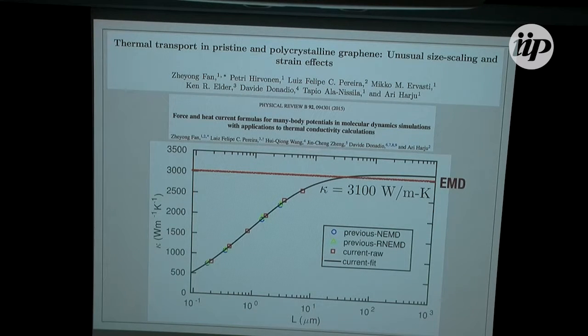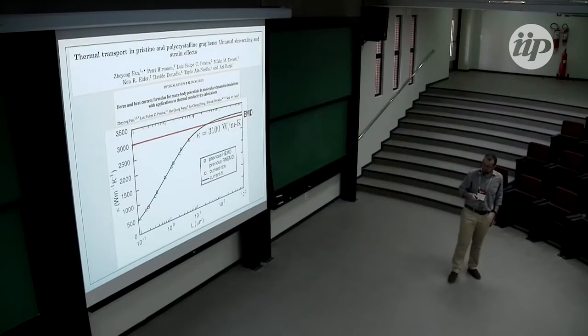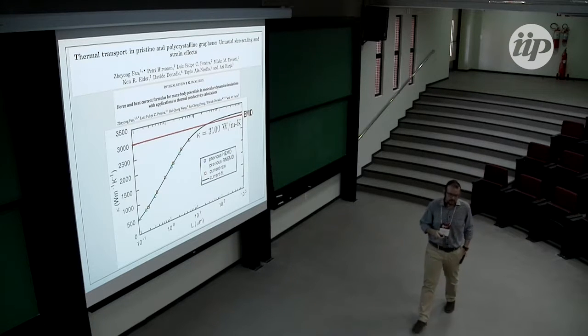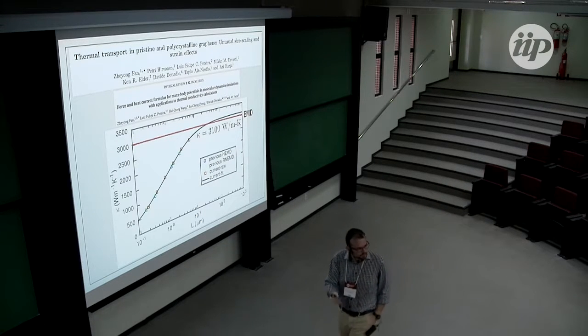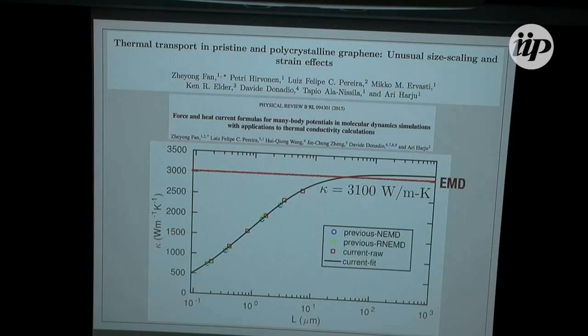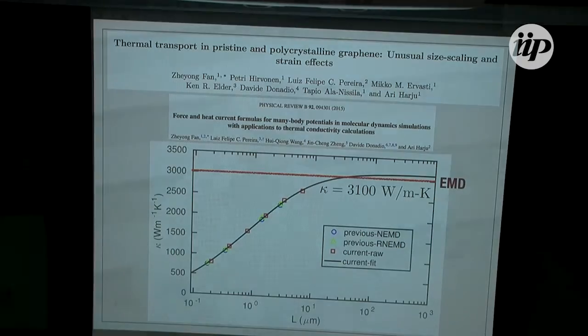Now the thing is, in this paper here, we took all these different formulations and showed that they are all equivalent, with the exception of the expression that is used in LAMMPS. So the heat flux expression that is used in LAMMPS is based on a decomposition of the atomic stress, which is only really valid for two-body potentials, like Lennard-Jones. It's not valid for many-body potentials like Stillinger-Weber, Tersoff, ReaxFF, or whatever. So you cannot calculate the heat flux in equilibrium MD correctly from LAMMPS.